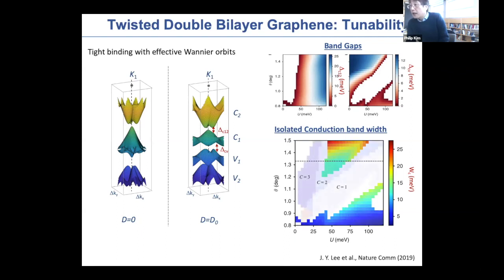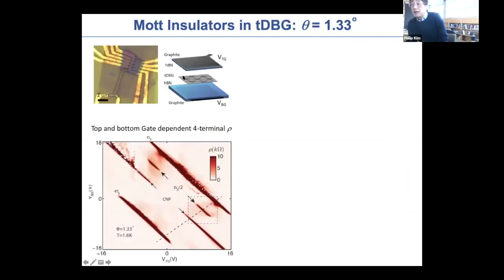In fact, this idea works. So this is a twisted double bilayer sample. And here we need two gates, top and bottom, to control both the filling and the displacement field. And you start to see that at the charge neutrality point, you open up a gap, which is basically a single particle gap, that again, by applying the displacement field, the gap opens up. And at full filling, there is also a gap that opens up. And again, this is the single particle effect that I just mentioned, that the moire superlattice will create this band folding, and they create the single particle gap.